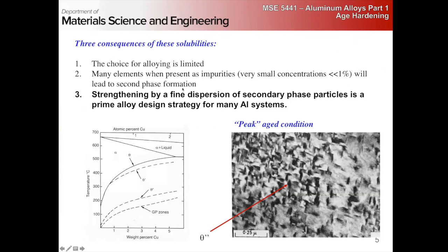These intermetallics are typically brittle and destroy properties if we allow them in too much. Sometimes they can help, like with fatigue resistance in aluminum copper alloys. A little bit of intermetallics, if we can get them to nucleate homogeneously, breaks up our slip. And basically because of this, a lot of our alloys are precipitation strengthened.